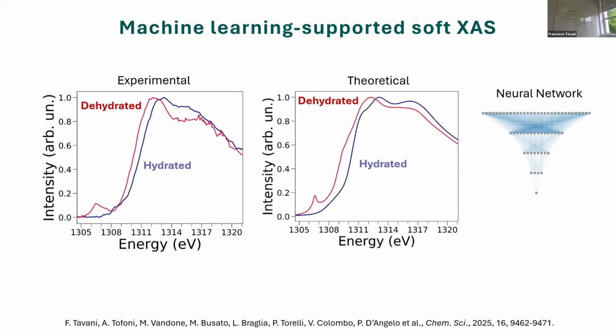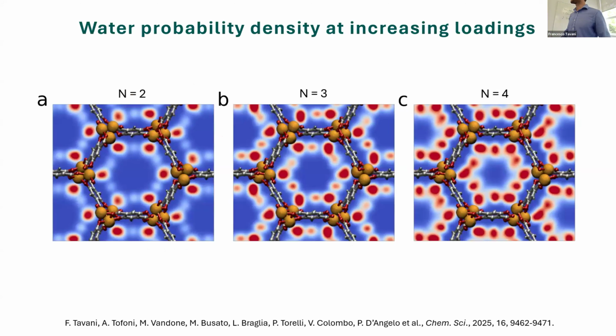And there's also this bump here, which is present in the spectrum of the hydrated MOF, but not present, or at least less intense, in the one of the dehydrated MOF. And the theoretical curves, at least qualitatively, reproduce this trend quite well. And the important thing to note is that this pre-edge peak is actually due to the inclusion in the model of 5-coordinate magnesium sites. So a part of the magnesium sites loses the water molecules directly coordinated to them during the thermal dehydration process. And we actually estimated the amount of open magnesium sites to correspond to about 20% of the total number of magnesium sites in the MOF.